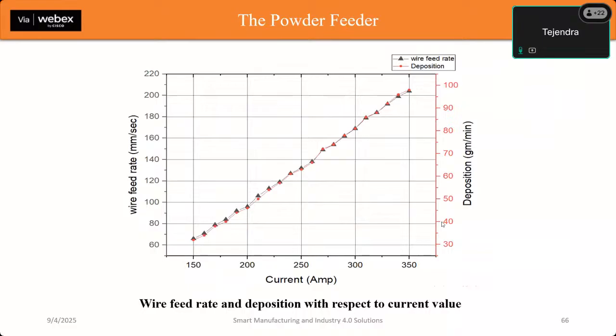Also, when we are using the powder, we have checked and experimented that the amount of powder and the amount of wire should be equal for the most efficient deposition and for defect free deposition. So we have tested the wire feed rate, the speed at which the wire is melting, as well as the current that is being fed for a particular wire feed rate, and the deposition that we are getting.